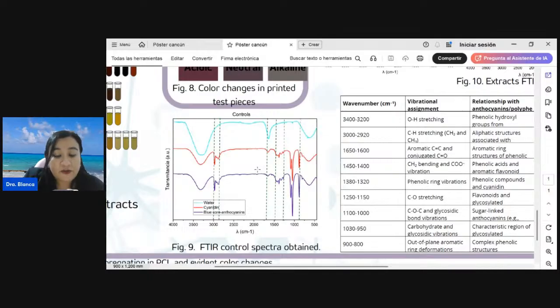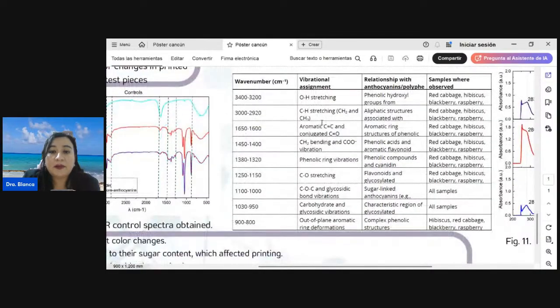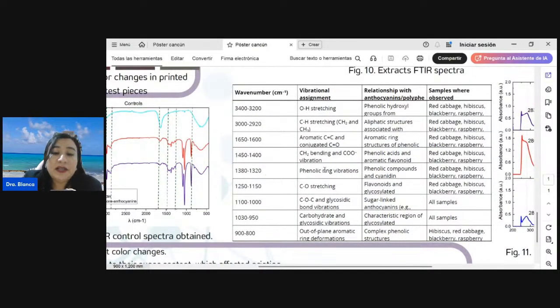Regarding chemical characterization, FTIR analysis provides evidence of the successful extraction of anthocyanin-related compounds. We found in this table the vibrational assignments, especially 1,380 to 1,320, the phenolic ring vibration compounds and cyanidin. We have it in cabbage, hibiscus, blackberry, and raspberry. We found in the 1,250 and 1,150 flavonoids and compound glycosides in red cabbage, hibiscus, blackberry, raspberry.